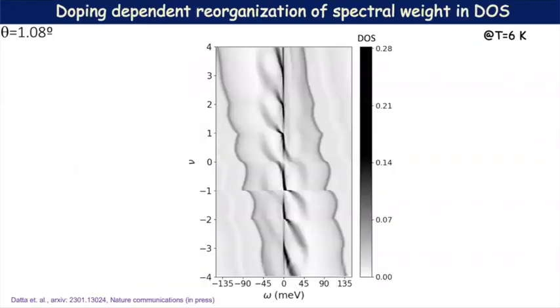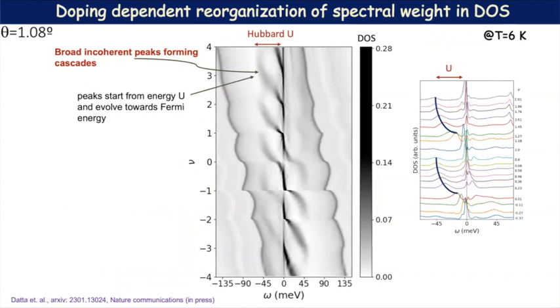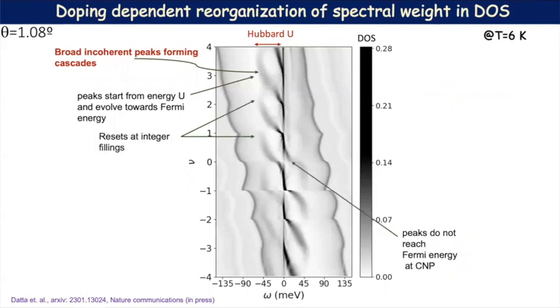So this black and white map is the density of state. On the Y axis, I have the filling factor, and on the X axis, I have the energy. You can immediately see these broad peaks, which are basically the incoherent Hubbard peaks, forming these cascade-like features. These peaks start to form at an energy U, which is the Hubbard U of the AA orbitals, and then they move this way as I change the doping value, shifting towards zero energy. They reach zero energy close to the next integer filling, where we also have this reset where the Hubbard peak reappears.